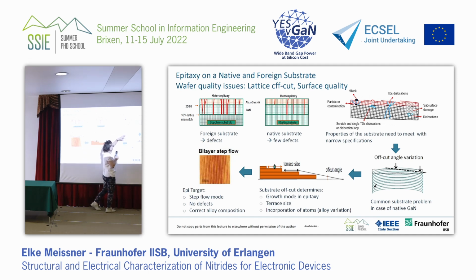So the substrate itself has some narrow specifications that you have to reach, and the common problem is out of these narrow specifications. Now, this off-cut angle determines the step flow. Actually, it determines the width of the terraces and the height of the terraces. This is determined by the off-cut angle. This is what epitaxy will create in terms of terrace size. So how fast your step flow runs over the surface.